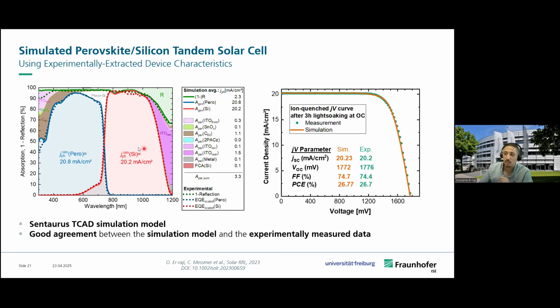As I said, you can see that the silicon is currently limiting the JSC, and therefore the JSC is 20.2, because it's set by the lowest subcell. You can also see that the C60 really has a high parasitic absorption, and this in a last step allows us to derive how we can optimize our device. Now that we have made this model, in a final step we can start to remove the constraints which we have put in order to see every loss channel, and what it can bring us in terms of efficiency improvement.